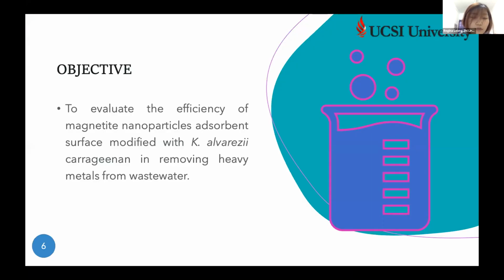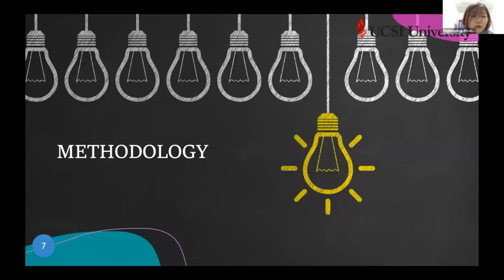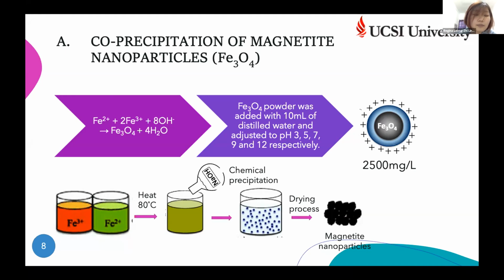Hence, this study aims to evaluate the efficiency of magnetite nanoparticle adsorbent, surface modified with Kappaphycus alvarezii carrageenan, in removing heavy metals from wastewater. So firstly, we'll go into the methodology. We will carry out co-precipitation of iron(II) chloride tetrahydrate and iron(III) chloride hexahydrate to form magnetite iron oxide. Chemical precipitation was achieved by adding sodium hydroxide. Then the yellowish mixture will turn into a reddish brown solution, then convert to black suspended particles.